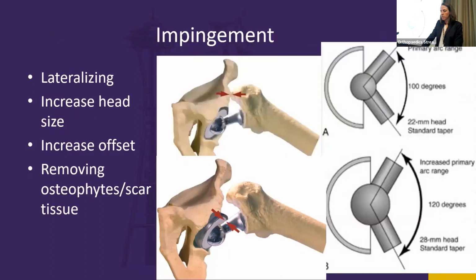And impingement. So impingement can occur between any two non-articular surfaces, and it can have several sources. So over-medializing the cup can lead to impingement. Soft tissues, including scar tissue or bony sources like osteophytes, can be a source of impingement. Spine factors, as we just mentioned, can be a source of impingement, including sagittal balance or loss of lumbar mobility. And then treatment requires addressing the cause of impingement, obviously with either component repositioning, lateralizing the cup or head center, increasing head size, which leads to increased range of motion prior to impingement, and increasing offset or neck length, as well as removing any of those bony or soft tissue causes of impingement.